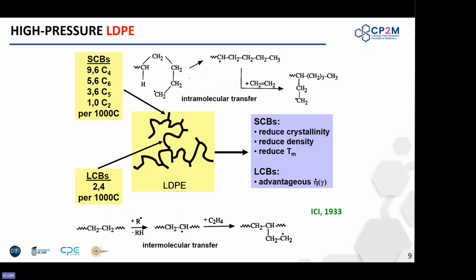And you have two phenomena that coexist during this polymerization. It will generate short chain branching and long chain branching. Okay, so you can have transfer, some kind of backbiting that would give you a C4 chain branching. But you can also do a transfer anywhere on the polyethylene chain. That would give you a long chain branching. These two things are very important, in particular the long chain branching, and it's because of the processing.